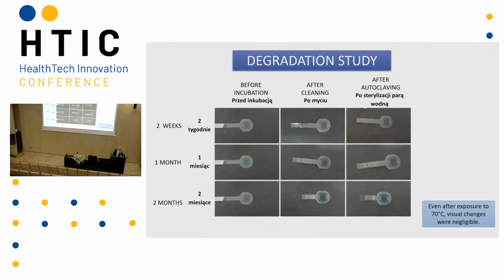We also did the degradation study. We included the conditions of reprocessing for surgical instruments, like cleaning and sterilization in autoclave. The sensors are very resistant to high temperature. Even at a temperature of 70 Celsius, the visual changes of the sensors were negligible.